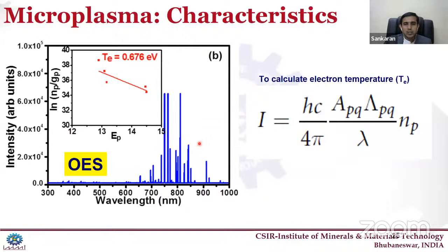From here, using these equations, we can calculate the electron temperature. So the electron temperature is very important in a plasma. This temperature that we are measuring here is a room temperature plasma only. So it's not like a thermal plasma, but the electron temperature is much higher actually. So we are getting an electron temperature of 0.6 eV, and then they have also calculated the density versus the energy. We can calculate the electron temperature from here using this equation. So the electron temperature that we have calculated for the argon lines is 0.6 eV. So this is low compared with the argon electron temperature from the other plasma generation systems.